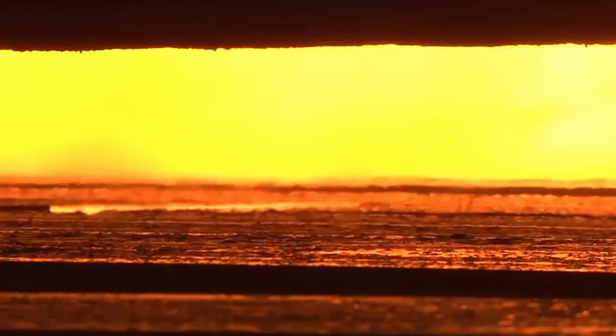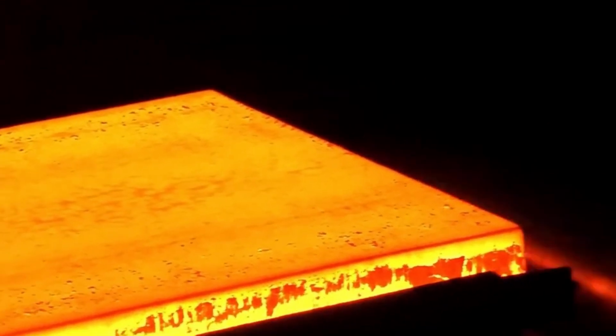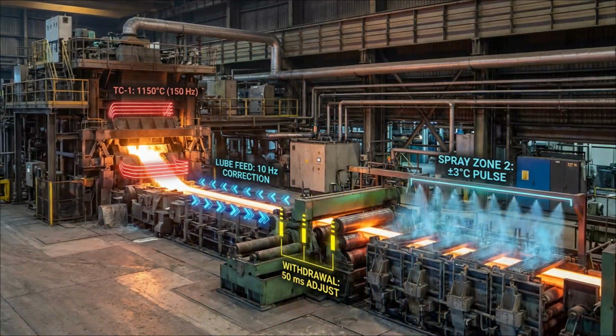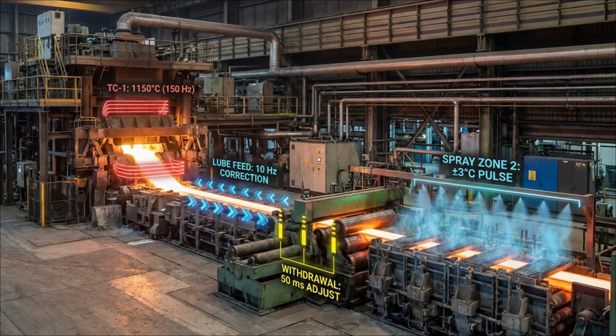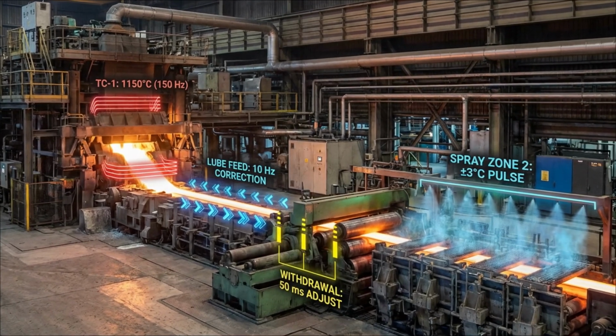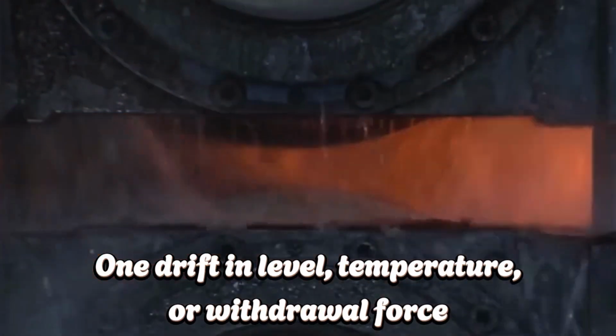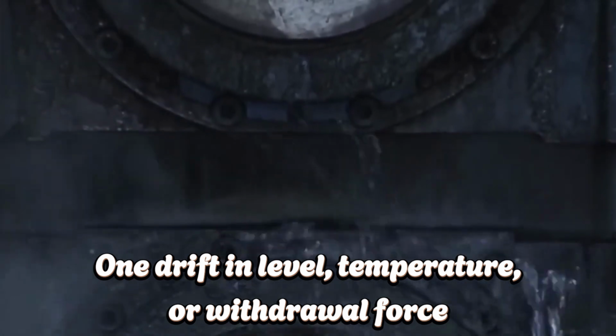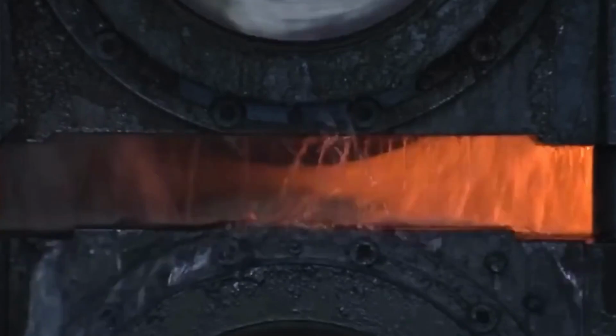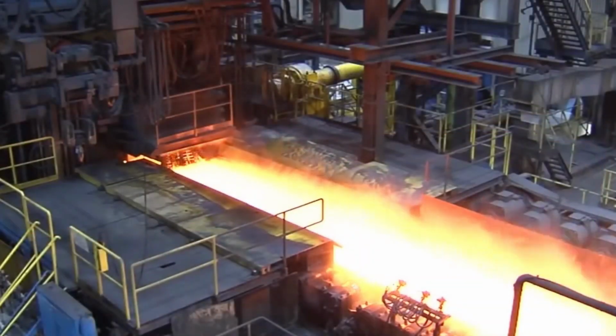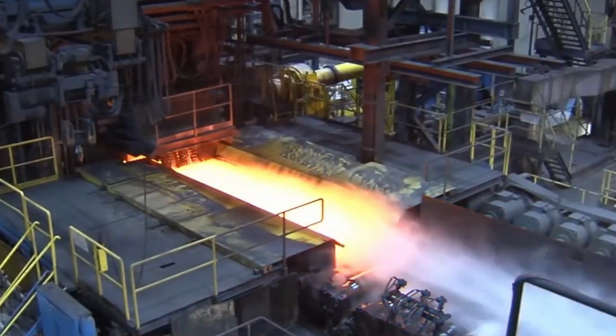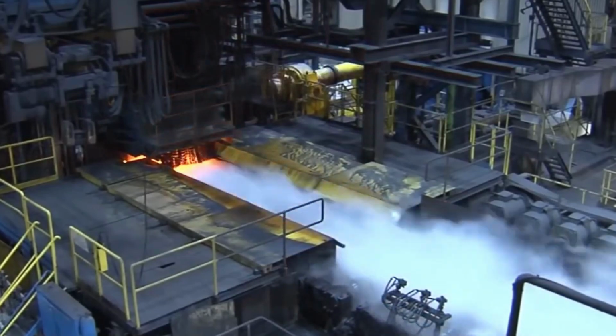Steel beams look solid, but their structure is born while the core is still liquid. Every minute, molten metal moves from ladle to tundish to mold to rollers to straighteners to reheaters to roughers to finishing mills. One drift in level, temperature, or withdrawal force, and the beam fails before rolling ever begins. If the flow entering the mold is unstable, the shell never forms evenly.